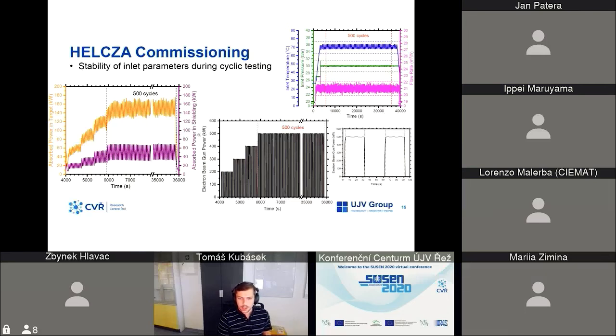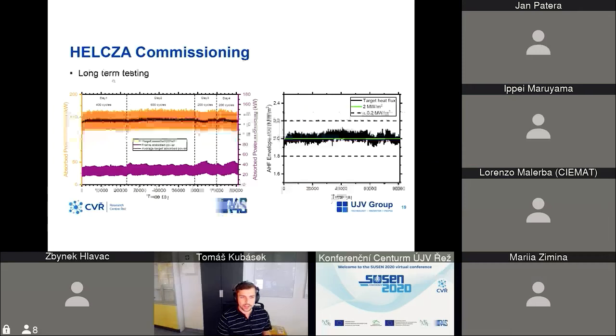Here is the long-term testing, which took 4 days in total, 1,400 cycles, and the black line here. We were trying to reach the high heat flux of 2 megawatts per square meter, which we calculated by taking the average target absorbed power over one cycle, which is 60 seconds, and this value should be half the power input in the first half of the cycle when the beam is actually radiating the target. So if you multiply this value by 2 and then divide it by the size of the window, we should get 2 megawatts per square meter, which we almost got here.